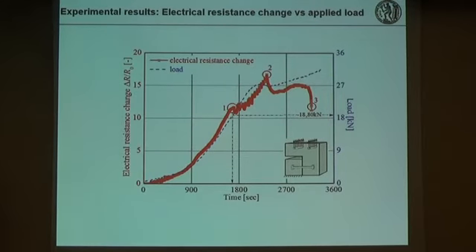Looking at the results of the electrical resistance change in comparison with the applied load, the electrical resistance change is the red line, while the applied load is the blue line. It is observed that the electrical resistance is changing analogous to the applied load up to point 1. This is a very encouraging result, which shows that this technique can be used for monitoring the stress strain of the restored marble epistyles. After point 1, there is this peculiar response of the electrical resistance oscillating up and down